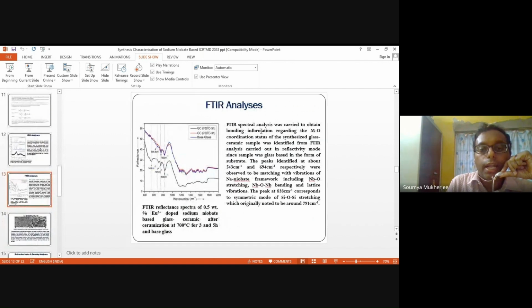Now, the FTIR analysis has been carried out. We have utilized reflectance mode, and we have tried to analyze the metal oxide coordination systems, and we are getting the comparison between the base glass and the glass ceramized at 5 hours and 3 hours. And we are getting peaks identified at 543 centimeter inverse and 694, which correspond to some sodium niobate systems and niobium oxide systems.